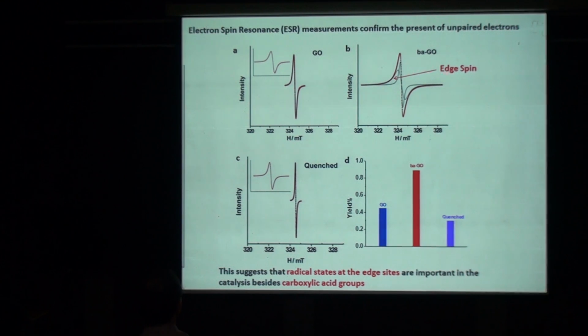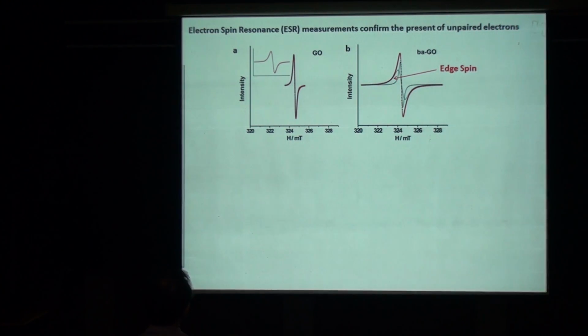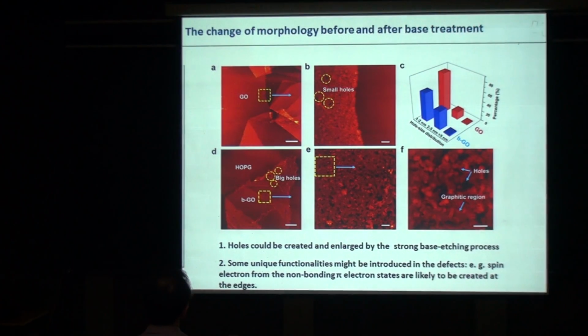If we do a chemical reaction to quench the edge spin, which we can do, we add some chemical molecule. There's a diazonium coupling reaction. The organic molecule goes to the edge, quenches this edge spin, then we find the catalytic activity is quenched. Now once you quench the edge spin, you don't see it, it becomes very sharp. So this edge spin, due to these defects, is very important for the catalysis.